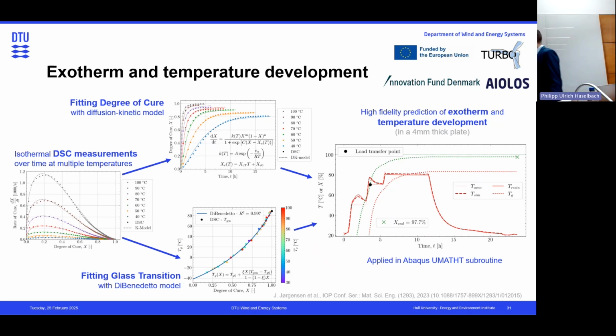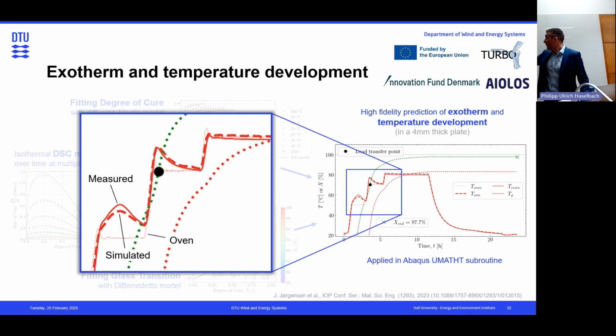Then he built up a user subroutine coupled to the commercial tool Abaqus, where we can model it. And of course, for doing that, a lot of characterization was needed in the laboratories as well to make the models reliable. But as you can see here, the simulation matches quite well. You have the temperature of the oven, and then it's measured how it is predicted, and more or less the measured curve is following the simulations, or let's say the simulation more or less can predict what we have measured there.